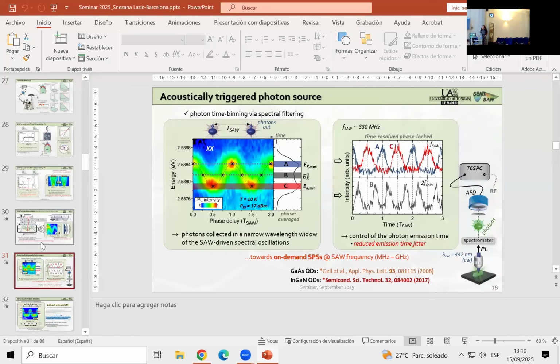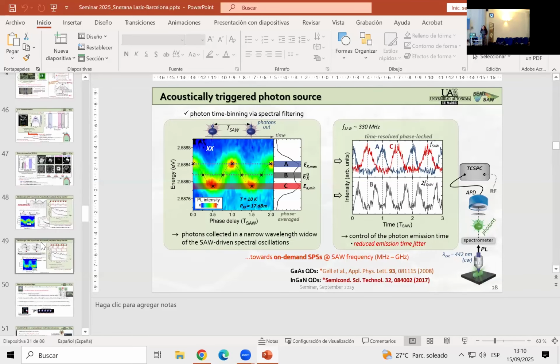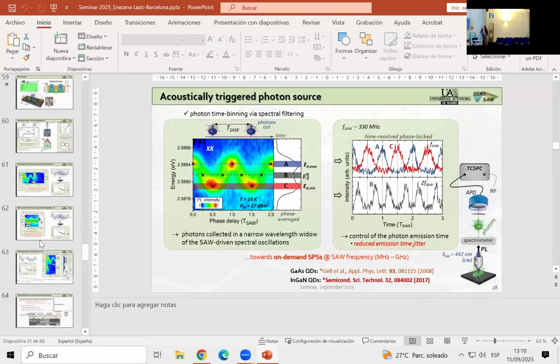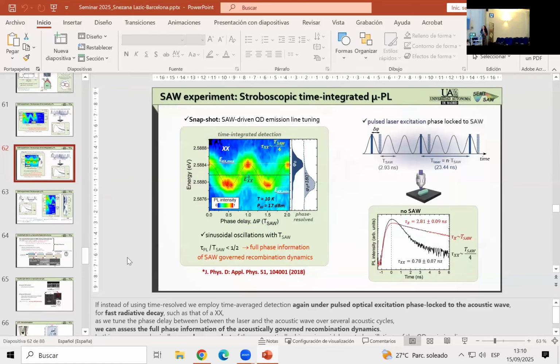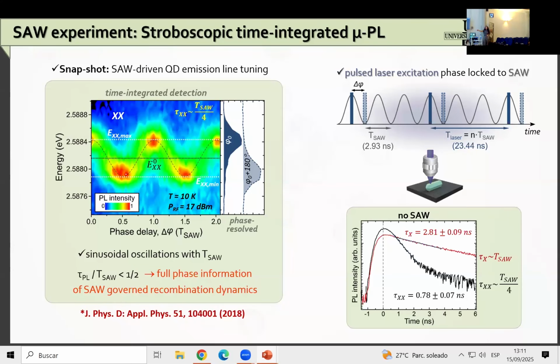Okay. So this is what you get from an exciton and bi-exciton when no acoustic wave is applied. So that's basically the decay. And then on the transparency I showed before, if you apply the acoustic wave, you would see those sinusoidal oscillations, right, during decay. Now, obviously, we have a different lifetime in the case of exciton and bi-exciton. So bi-exciton has approximately half of the lifetime compared to the exciton.